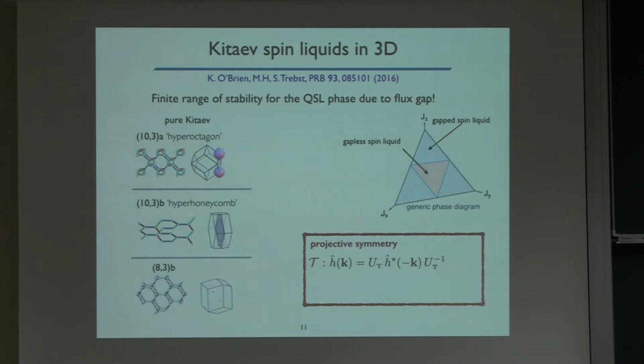Let's take time reversal, for example. So time reversal, you usually think that it relates the Hamiltonian at k to a Hamiltonian at minus k. And so that's the relation you're all used to. And if time reversal is implemented like this, then you always get a gapless spin liquid with a nodal line. The point is, it doesn't have to be implemented like this. It can be implemented differently, namely with an additional translation in momentum space. So this vector k0 here, that is half a reciprocal lattice vector. And depending on the lattice that you look at, this k0 is not 0. And if it's not 0, then you generically will stabilize Majorana Fermi surfaces.